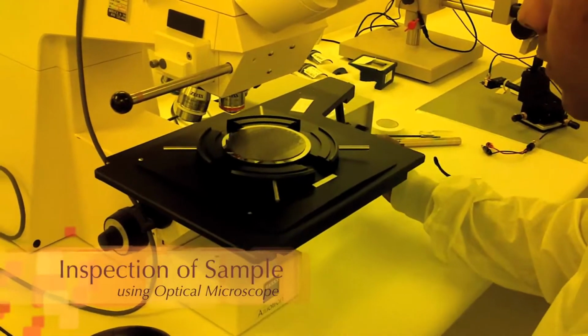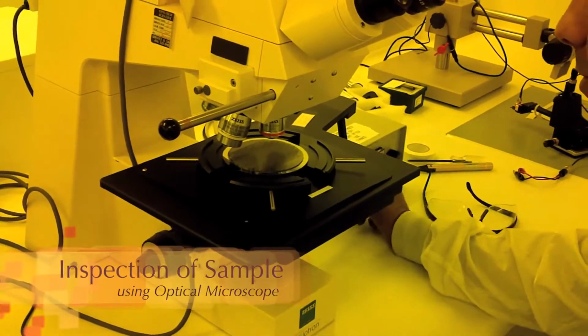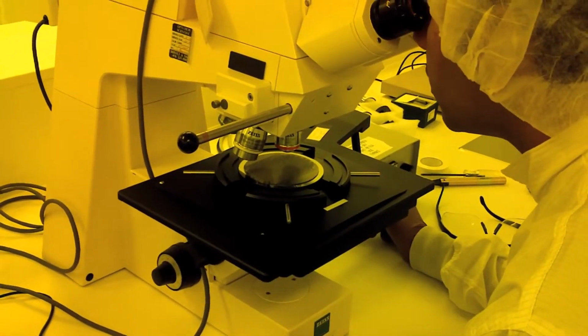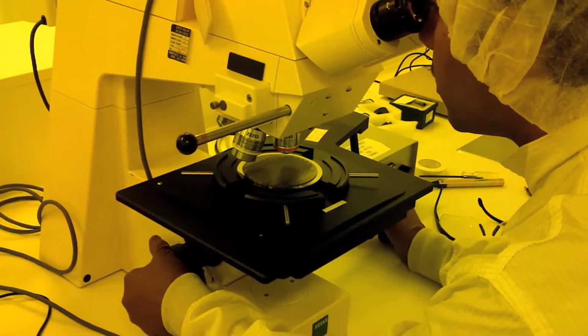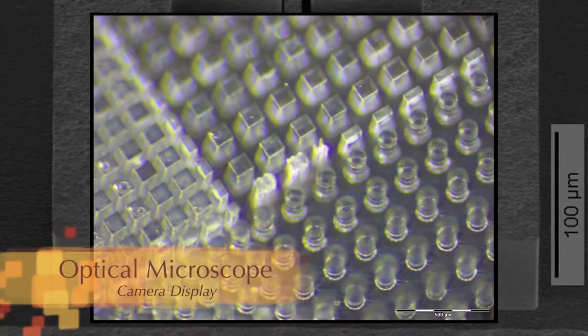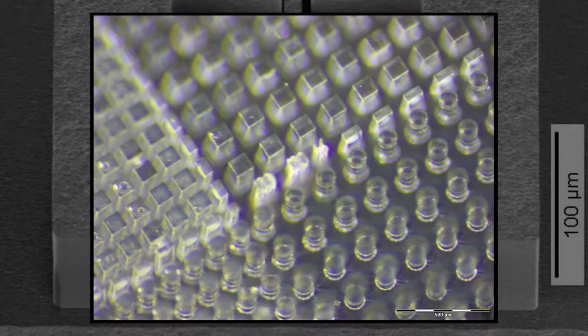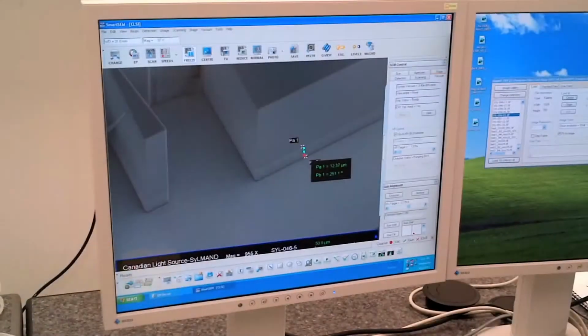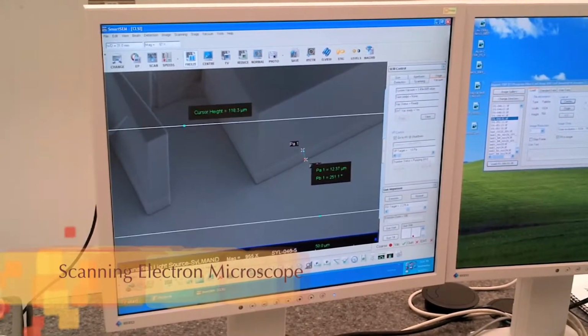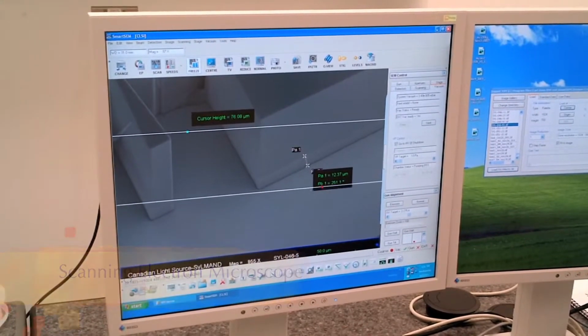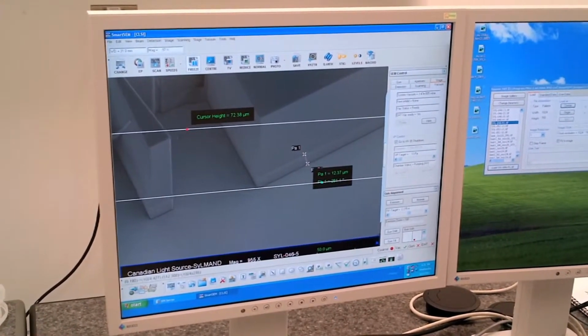At the end of the development process, a detailed inspection of the sample is undertaken to confirm the integrity of the pattern transfer and to look for defects from thermal effects or translation arising from relative motion between mask and substrate during exposure. If defects are identified, the causes for defects are characterized and the entire process fine-tuned to minimize and eventually eliminate the source of defects in subsequent runs. If no defects are detected, the sample is passed along to the metrology stage for imaging with a scanning electron microscope.